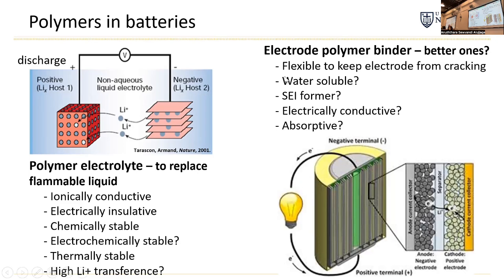So PVDF is soluble in organic solvents, so it would be greener for processing if we had aqueous or water-soluble binders. It would be better if our polymer binder was functional and was a good SEI former, so we get very advantageous surface chemistry. If the polymer itself was electrically conductive, this would be advantageous, or if it was absorptive for maybe species that are generated that we don't want to traverse the cell, that would be advantageous.